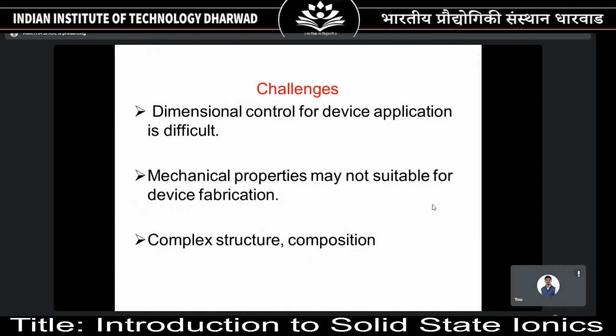Challenges. When you look into this perspective of solid electrolytes, the challenges are dimensional control. We cannot make the reduction in the dimension. Conductivity may be high, but unless you reduce the dimension, you cannot change the resistance. Resistance should be very minimal when you use it in a device. And mechanical properties may not be suitable for device fabrication. As I told, they may be fragile. And the structures are complex. The composition is complex. So one has to really have control of synthesis of complex structures and compositions.